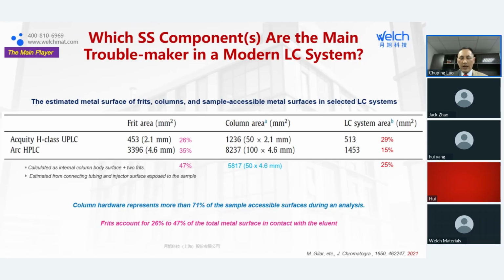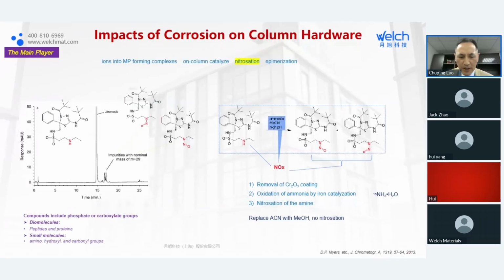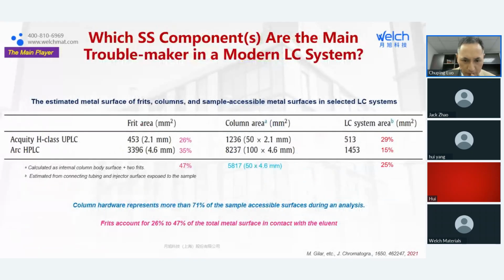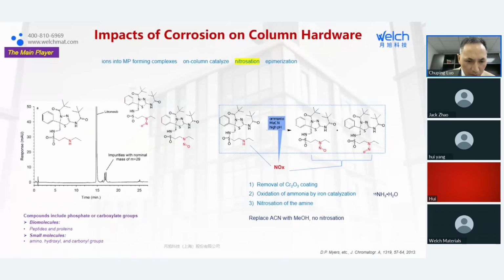So how much can this kind of corrosion impact the separation? On the left side, you see the compound they call the neutral compound, on the far left. It's a tall, beautiful peak. But on the right side, there are two split peaks. People never understood it at the very beginning, but then figured out this is the same compound, but nitrosation happened to these compounds, giving you two different configurations.